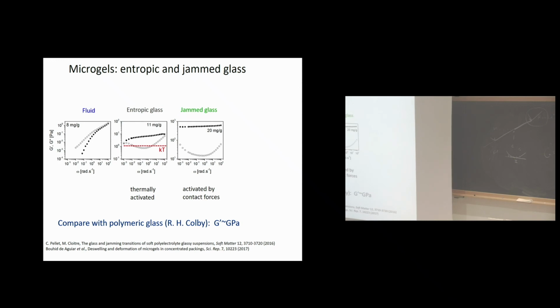And so you go from a liquid behavior to a glass, and then to a jammed glass. So then the modulus goes up dramatically. But look at the values. They're barely kilopascal. Compare the colloidal glass to the polymeric glass of Professor Colby. It is gigapascal, right? So this is one of the many reasons why colloids are nice, right? You can easily manipulate your glass.